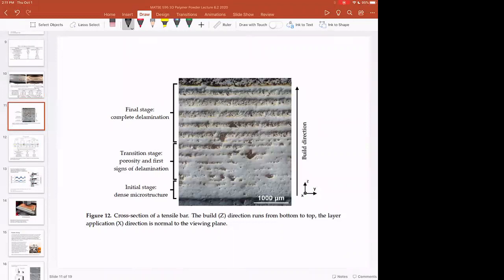The other thing that happens, and this is a really cool image, is that as you build this part, in the initial stage of SLS, so this is layer 1, and this is layer X, whatever it is. So you're building up this way, just as the arrow says. In the initial stages, you're getting a nice dense microstructure. You have some flaws, but not too many. But as you start to make the part thicker and thicker and thicker, because you're getting warpage, you have this delamination defect.